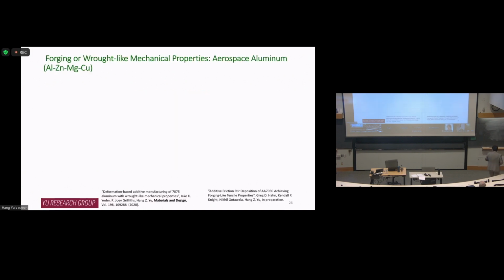So that's about microstructure evolution. How about mechanical properties? How does our process compare to fusion-based processes in terms of giving you good properties? One example I'm showing here is high-strength aerospace aluminum alloys. Those are 7000 series aluminum alloys. You have a hot cracking problem in the fusion-based process, so people in the fusion-based additive manufacturing field add nanoparticles to address this problem.